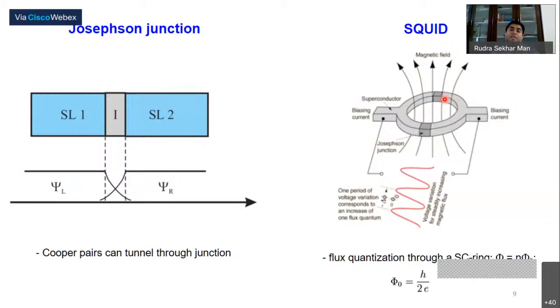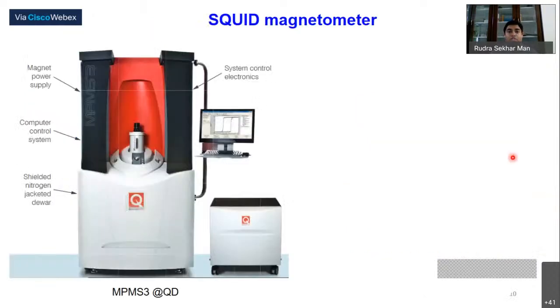Also, the magnetization you can measure with a simple electromagnet, that is also different. Like you have a sample, and then you use a vibrating sample magnetometer, you put a magnetic field, you vibrate your sample, but there the sensitivity is not that high. So that's the principle they use in the SQUID magnetometer. You can measure also 10 power minus 7 or minus 8 emu, electromagnetic units.